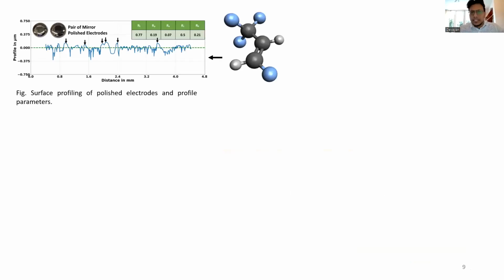So coming to the research behind the HFO gas itself. Initially we tried to manufacture electrodes in all different ways, having different coatings and mineral polish. But what we always saw, when we did the surface profiling, is this graph, which represents the surface profile and the distance which we measured. And these are the parameters according to the ISO standards. We always saw very minute microtips, no matter how good the finishing. This is one example, but some of them were even 1.5, 2, 3. So you have tips from 0.5 to almost 3 micrometers.